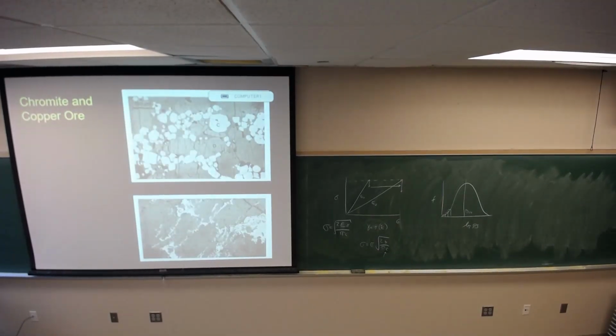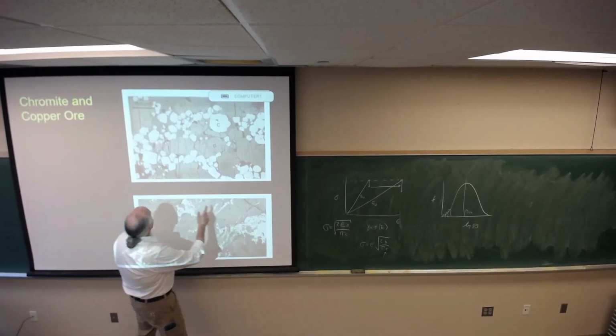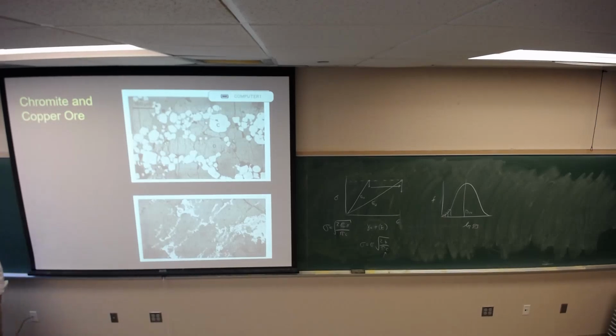The ore at the top can be crushed, and you liberate these chromite and olivine particles from each other. The one at the bottom, you're going to have difficulty doing that. There's a size bar here. It says it's 178 microns, which is interesting, and I assume they're both the same. There's 100 microns in the upper corner. But the problem is that because that microstructure is so fine, when you fracture that ore, you're not going to be able to break that out into discrete particles that can be separated. That's actually the foundation, or what drives the ability to do froth flotation, is that you can crush that ore into particles which are essentially one component rather than multiple components.